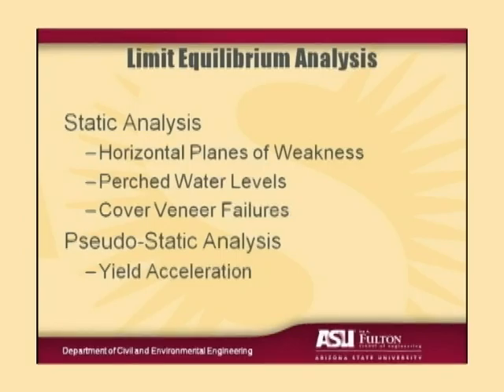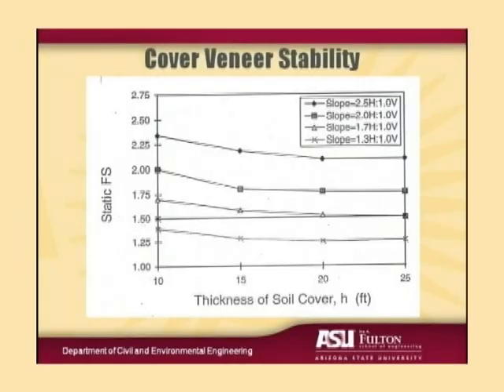Now, for the seismic analysis, we also then would evaluate what the yield acceleration was for a variety of different failure mechanisms. In the static analyses, the failure surfaces through the waste mass were all satisfactory. I think the lowest factor of safety we got, even on that steep north slope, was on the order of 1.9 to 2. So we weren't worried about the static stability of the waste mass. However, the cover veneer stability was problematic. As you can see, it depended on the thickness of the soil cover as well as the slope. And on those steep areas of the north slope, the 1.3 to 1.5 to 1 slopes, it was below what we considered acceptable, below 1.5.